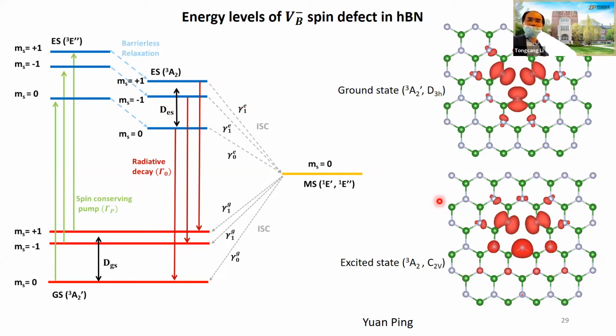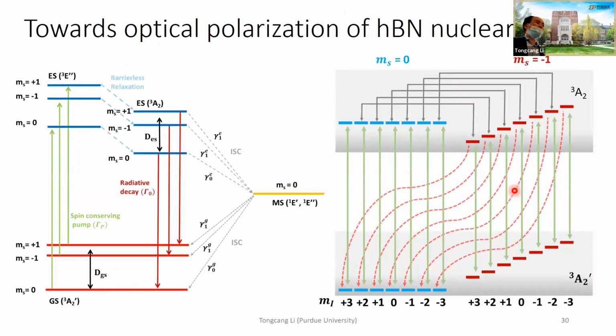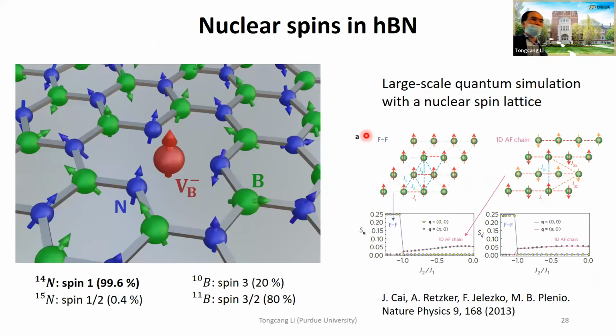First of all, Professor Yuan Ping's group calculated the spin density of the ground state. The ground state has rotational symmetry, the D3h symmetry, but the excited state has symmetry breaking, reduced to C2v symmetry. That will also affect the nuclear spin polarization. Now, if we really want to polarize nuclear spin, remember this is far more complex than diamond NV. We have so many nuclear spins surrounding the defect; all atoms have nuclear spin. The dominant ones will be the three neighboring nitrogens, and these are identical, so you cannot really distinguish them.